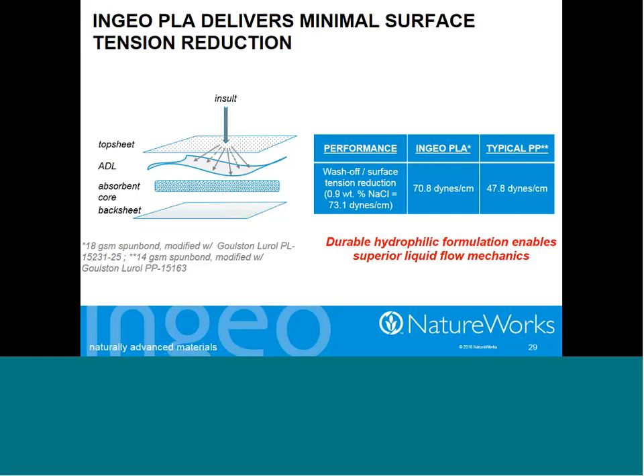And you can see here on the right-hand side, the property that's really a key feature here is the surface energy of PLA, almost 71 dynes per centimeter versus the very non-polar polypropylene down at 47 or 48. And that difference is important, or the high number for PLA is important for a couple of reasons. Typically, every fiber is going to have some sort of finish or treatment on it for processing and for use. And the high surface energy of the PLA helps that surface finish stick as well as be more efficient.